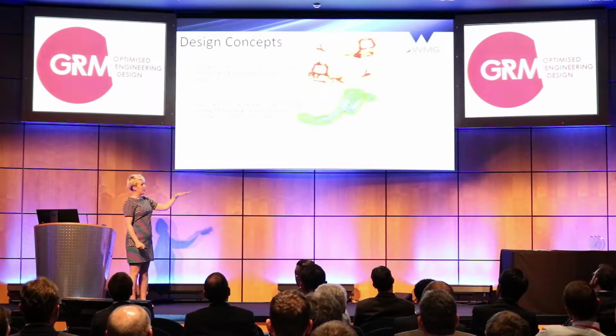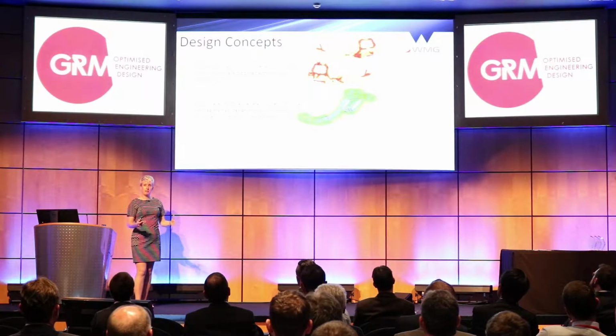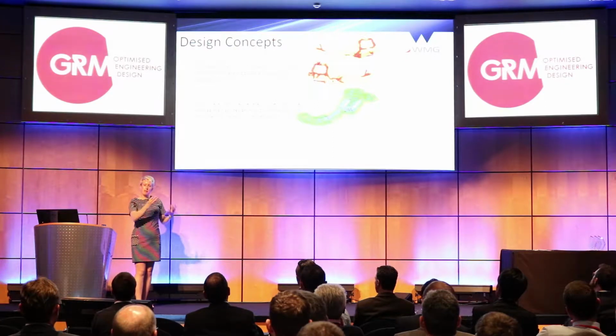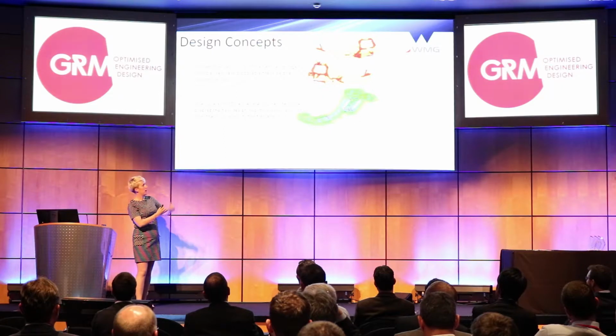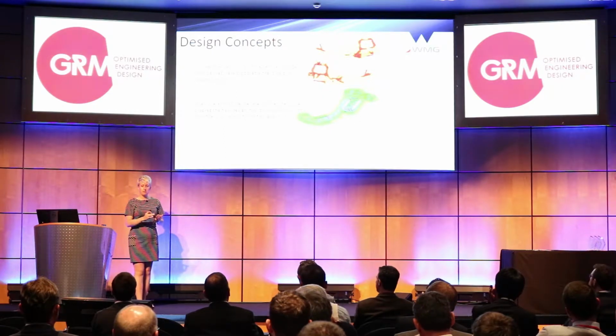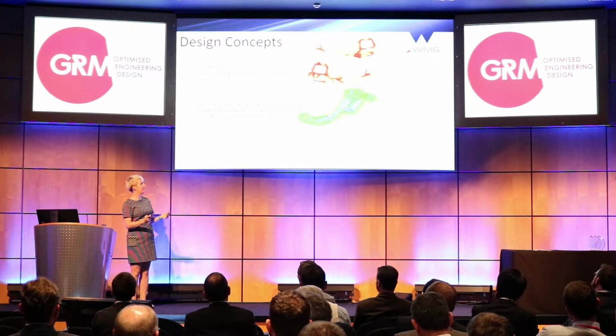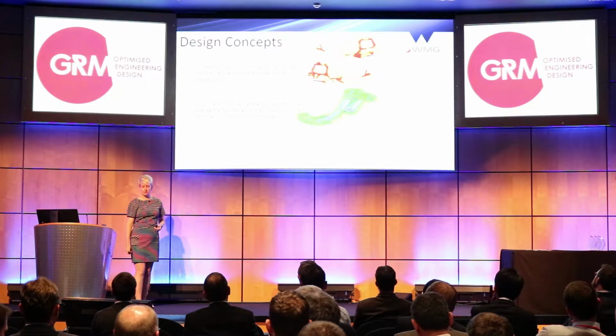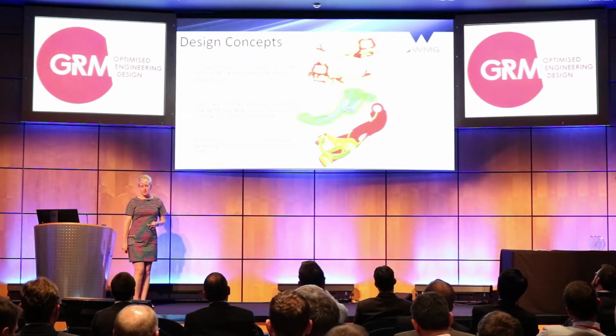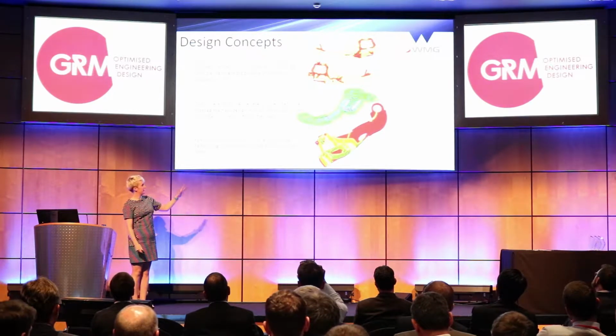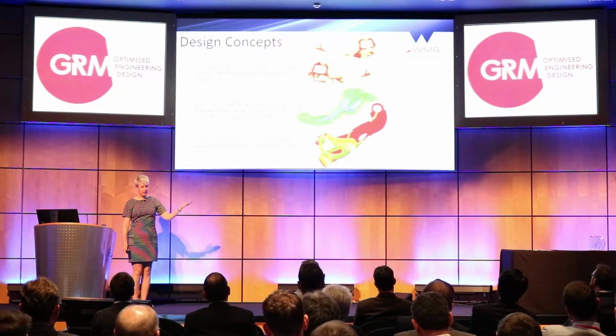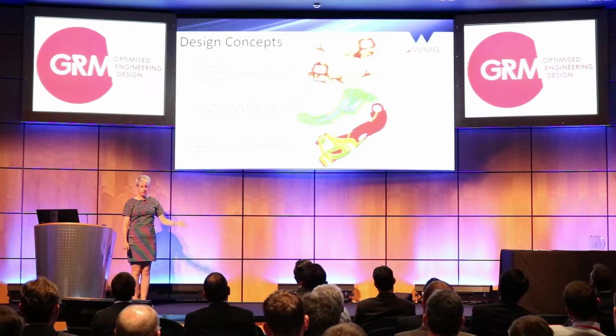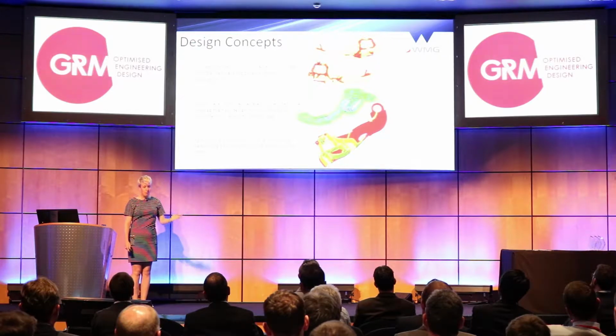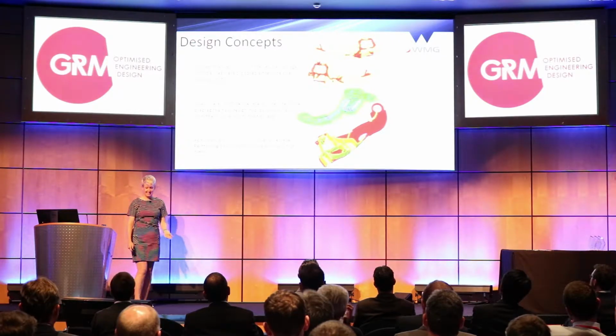However, that ski slope is too harsh. If you think about forming pre-preg materials, the draping, it's kind of like trying to drape a piece of paper. So you can't have these really harsh transformations because they're either unmanufacturable or you get wrinkles. So pre-preg and SMC again, this transition was then reduced. And again, all the SMC's on one side. So we're nearly there, but we didn't meet the strength requirements.